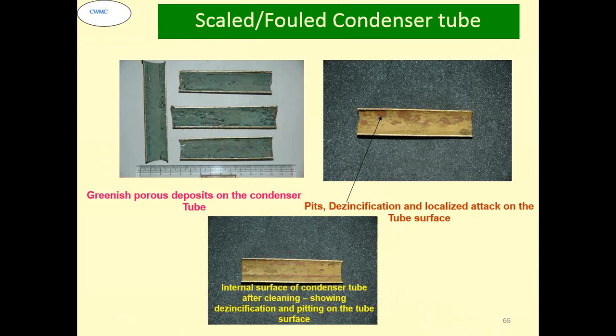What you see here is the greenish product. This is a typical fouling that has been caused by treatment chemicals, in this case ferrous sulfate, which is dosed as a corrosion inhibitor in a copper-based system in seawater. Now the same tube, if you see below, a severe corrosion has taken place, and you can see localized attack on the tube. Because of this, the tube starts puncturing and you start getting condenser leaks.